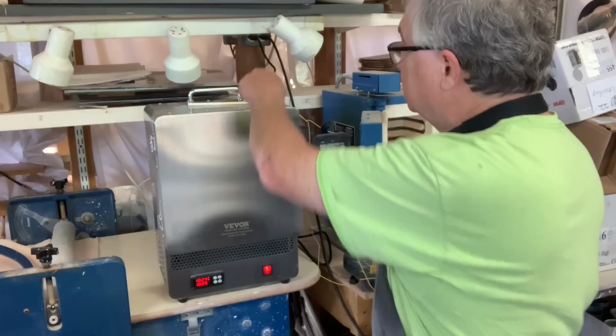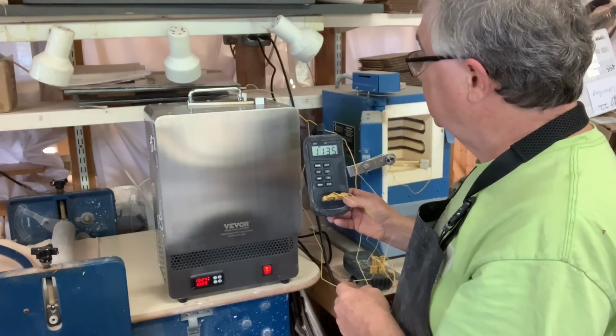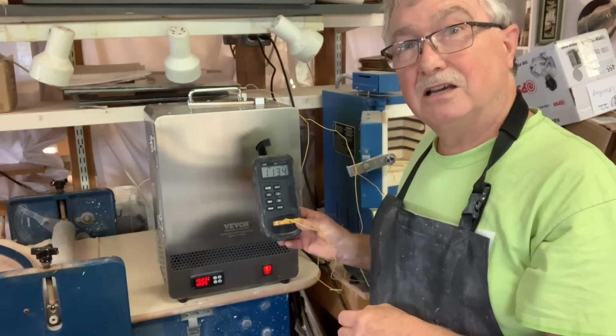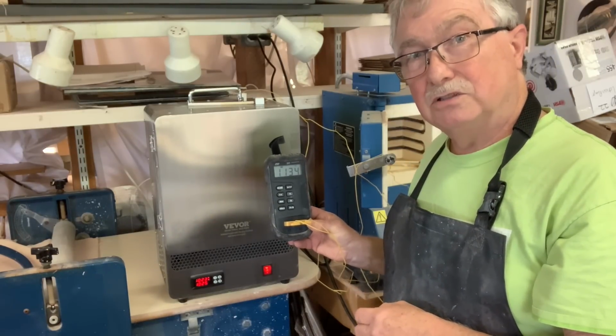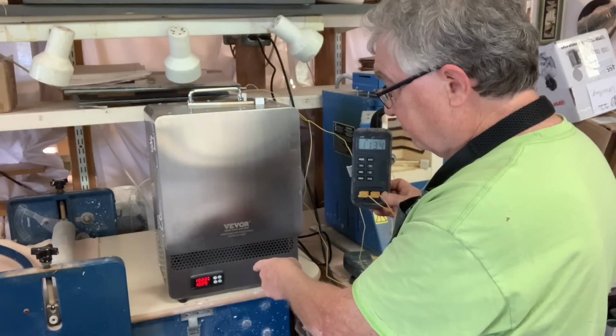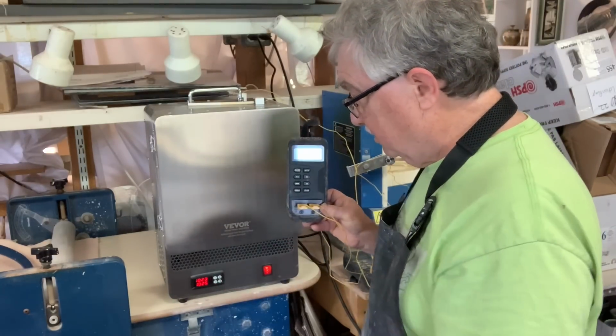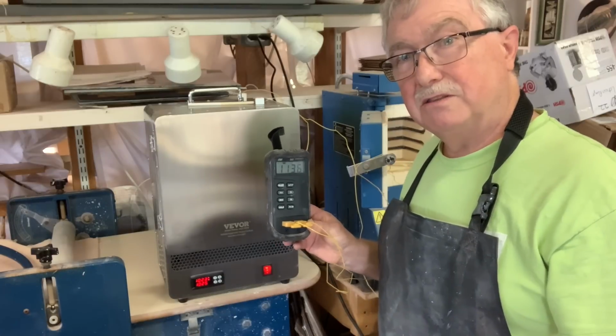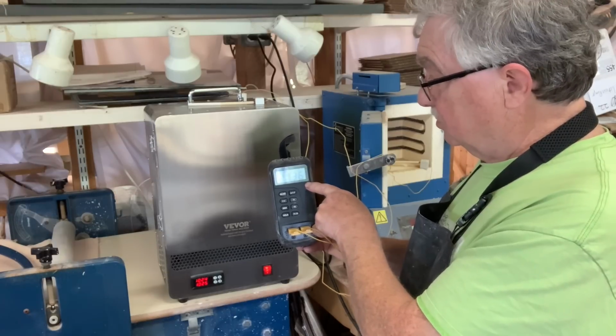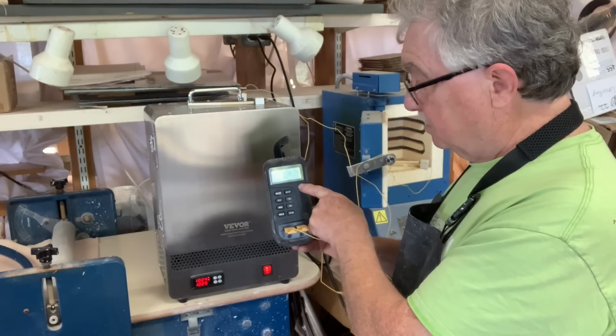Here's my pyrometer on the actual thermocouple that's inside, reading 1135 degrees centigrade. That's 110 degrees hotter than the thermocouple supplied with the kiln is telling you, which is reading 1023. I set it at 1025, but it's now reading 1023 because it's holding, so it's stabilizing out. So we're still 110 degrees hotter on my supposedly more accurate thermometer here.